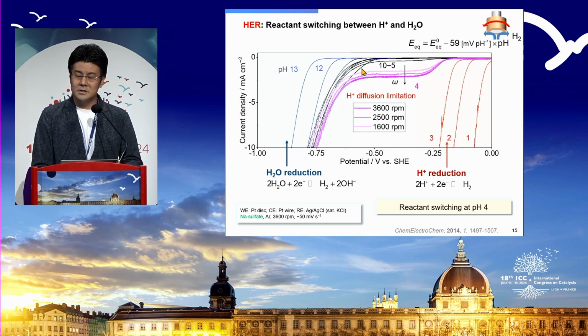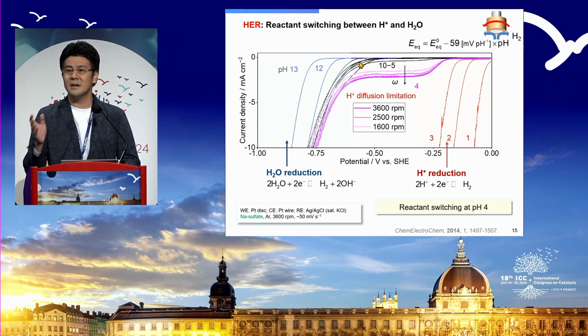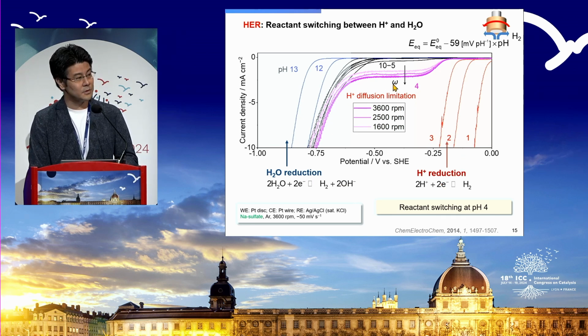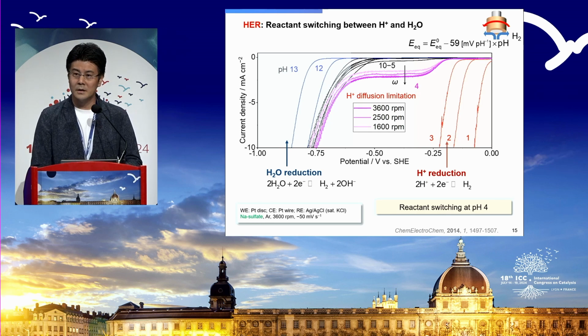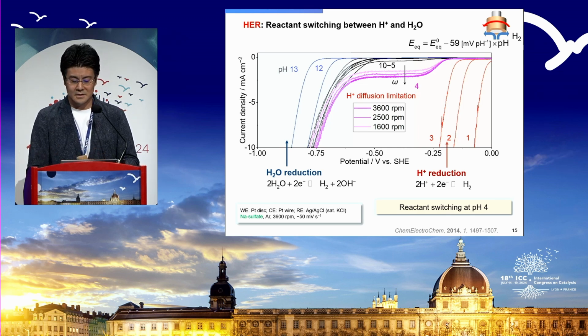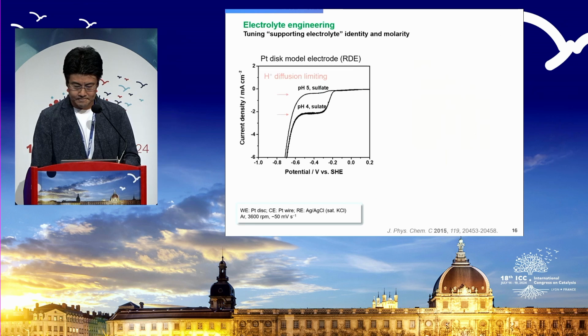Here you can also see the local pH: if you start with even 5, the local pH close to the platinum is around 10. You can learn from this figure. So yes, there is a reactant switching from the protons to water. And you can see that a large overpotential is required if you work in neutral pH conditions. If you switch the reactant to water, water is one of the most stable molecules. OH bond dissociation is quite challenging.